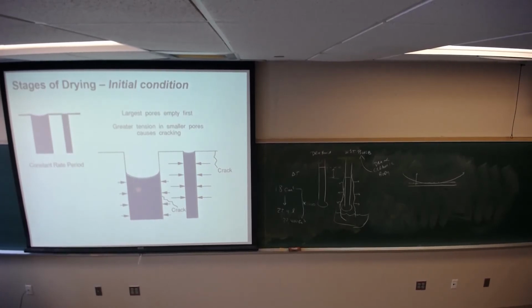And meniscus forces are such that this curvature that you have, and the evaporation rate is enhanced by that more gentle curvature compared to here. So then you evaporate water more in this condition, which gives you greater compressive stresses that cause then tension in the system and eventually cracking. Okay, you get greater tension in the small pores, and what it's doing is it's pulling this material away from here, and that's creating a crack in this direction.